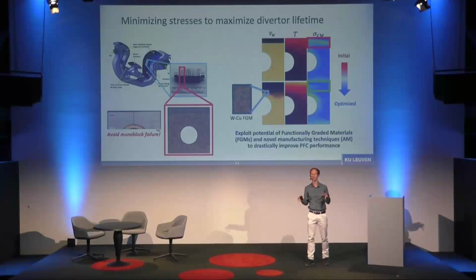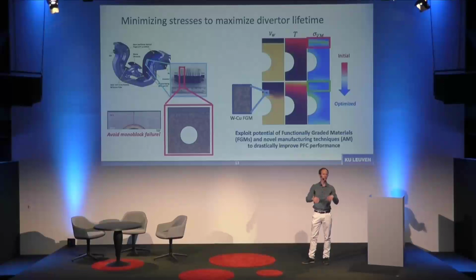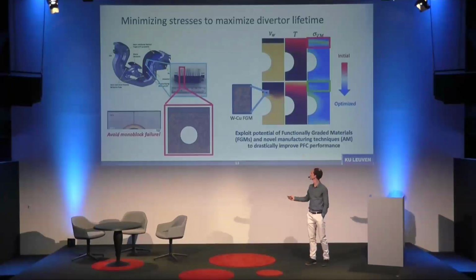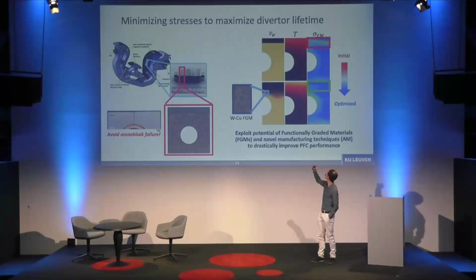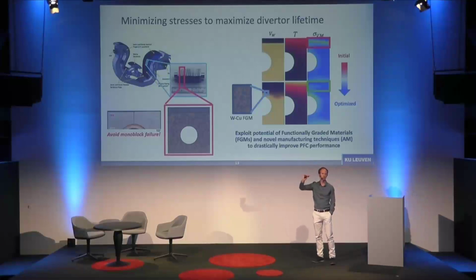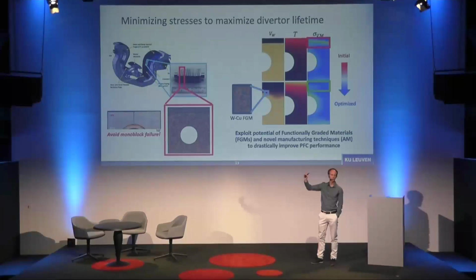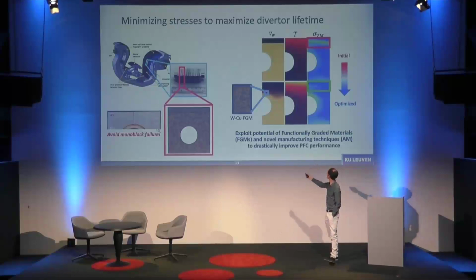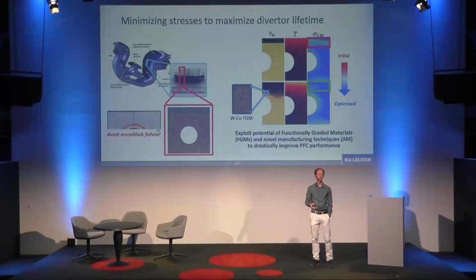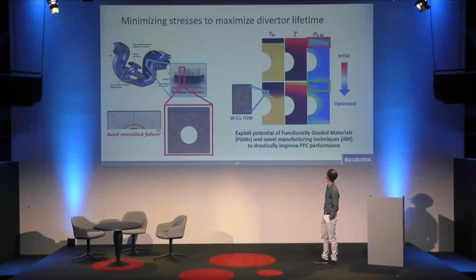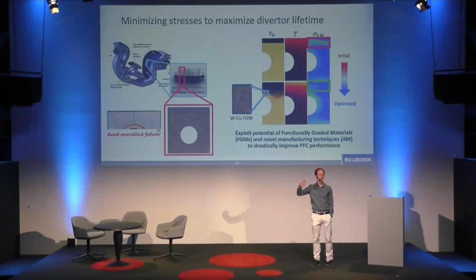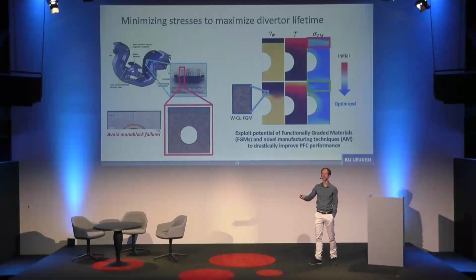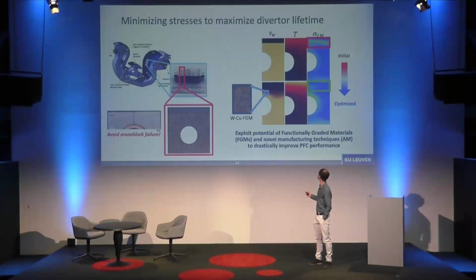So if you have additive manufacturing techniques, you can start really on a very fine scale designing the detailed structure of your materials, and you can somehow optimize the composition of your monoblock, going from the very top surface where you want a very heat-resistant material like tungsten to protect your component from the plasma, and then gradually transitioning into copper towards the coolant, which has very good heat conduction properties. And so if you do this change in a gradual way, you can avoid local stress concentrations, and therefore you can avoid problems like cracking and increase the lifetime of your component.